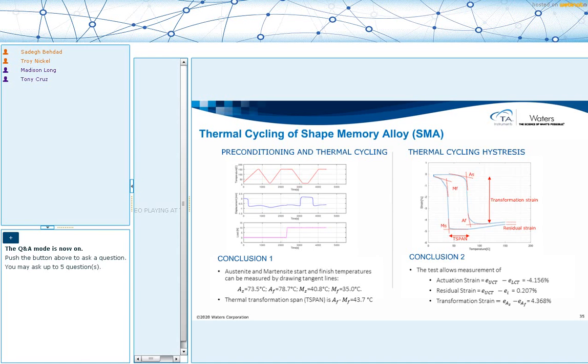So now, if you plot these data differently, this time we are plotting displacement, or strain, versus time on the right. Now we can characterize the four corners of this graph to establish the onset temperatures for martensitic and austenitic transformations, and we can measure the hysteresis, the transformation strain and the span. So basically, looking at the width and length of that helps us understand how much actuation strain there is in the end.